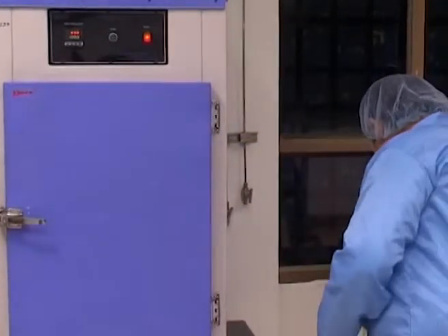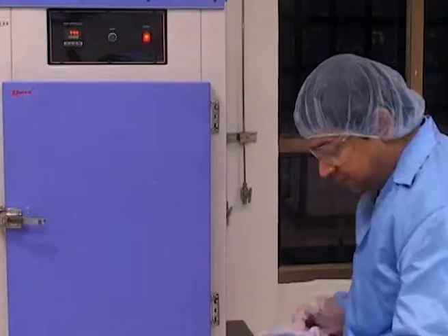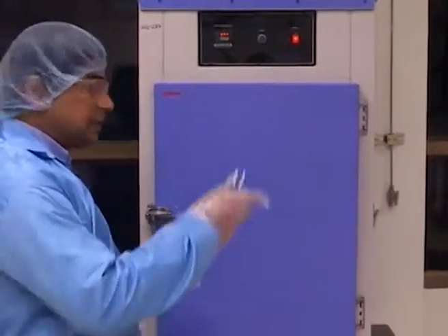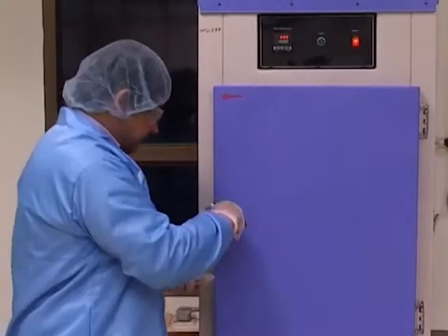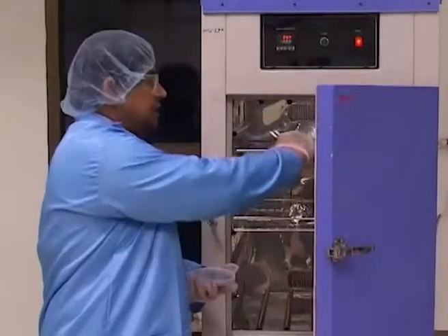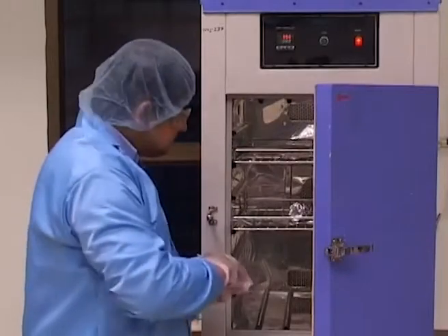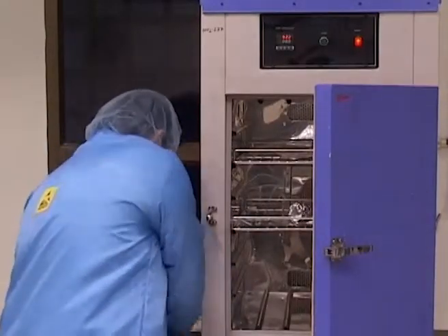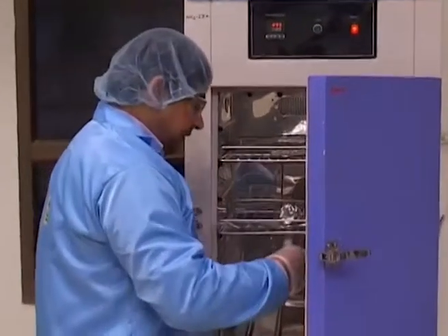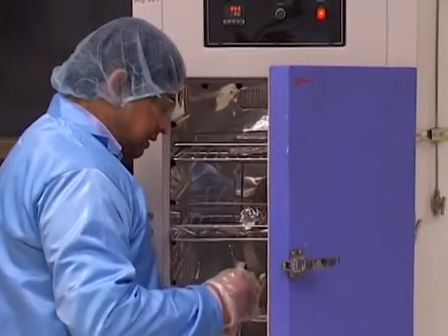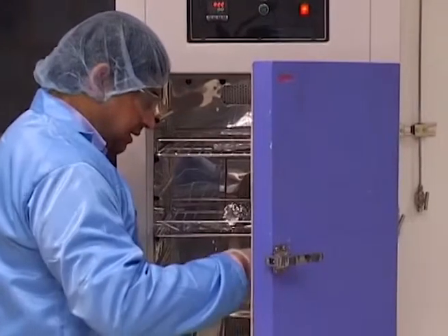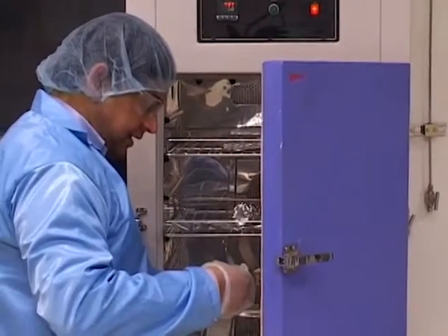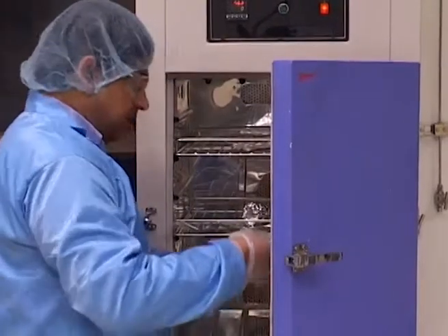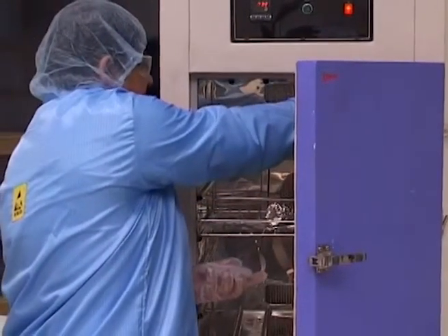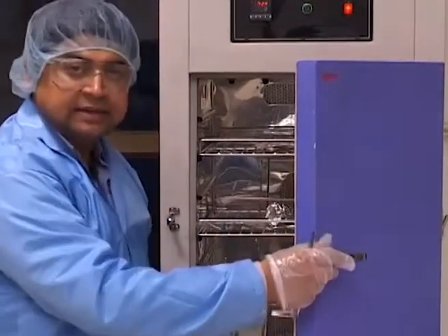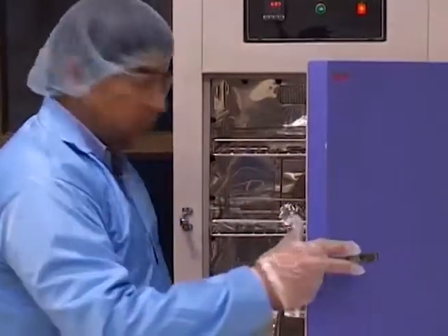So what we basically do is take the wafer box, which we pulled out of the fume hood after the piranha clean, and put an aluminum foil on top of one of these shelves, and then slowly load our wafer sample so that we can get it heated and remove any water if present on the surface of this wafer. The whole idea is to have a perfectly dehydrated surface of this wafer so that it can adhere well to the photoresist that we spin coat on top of it before doing photolithography.